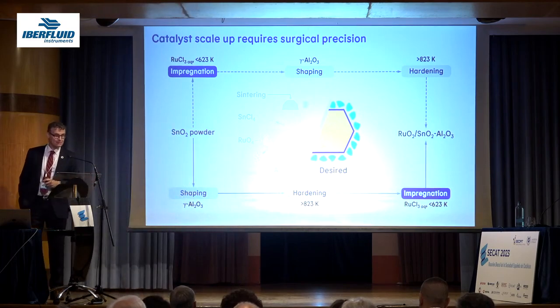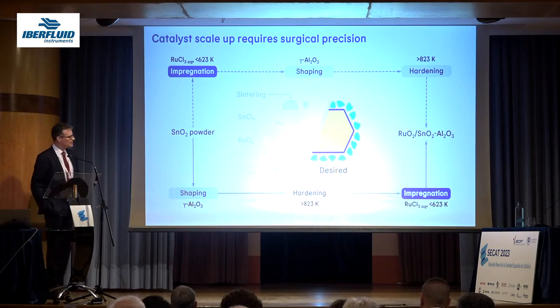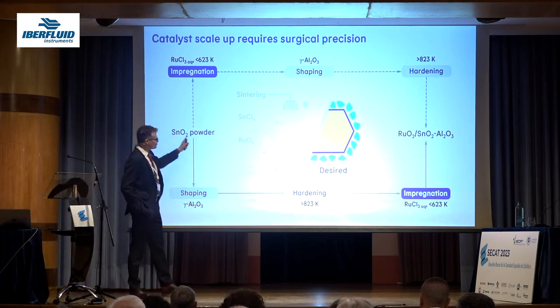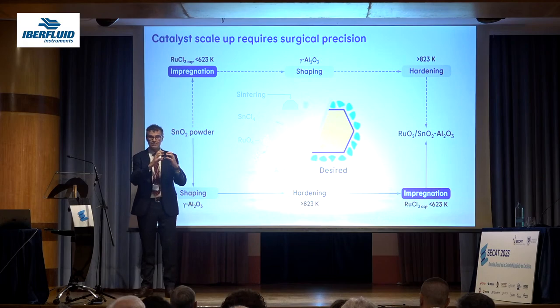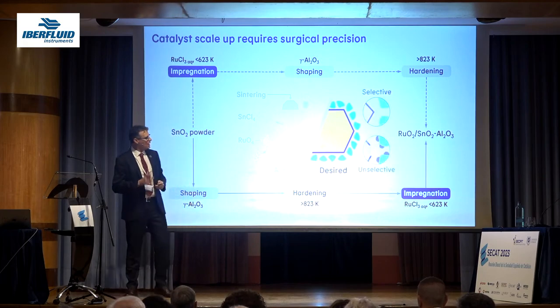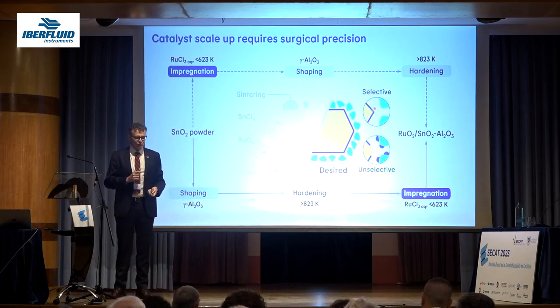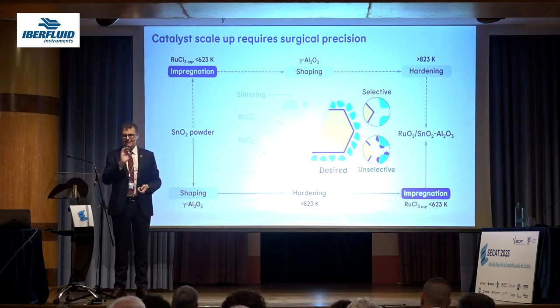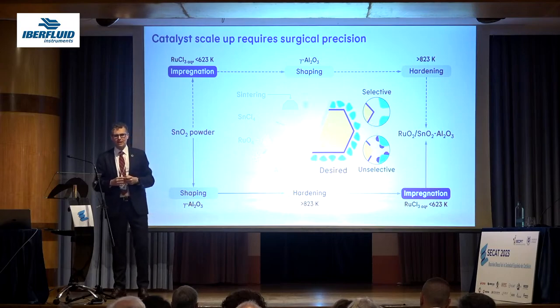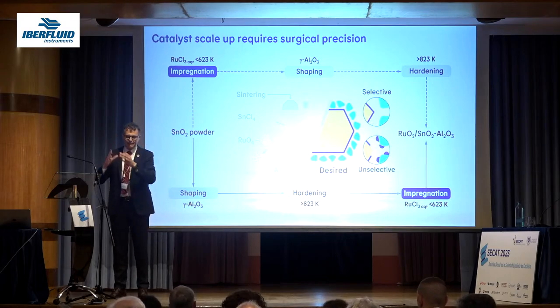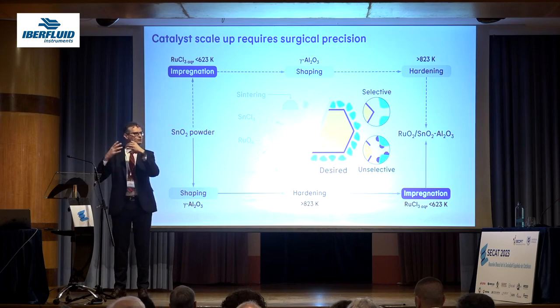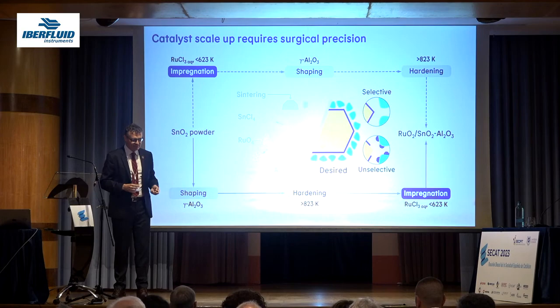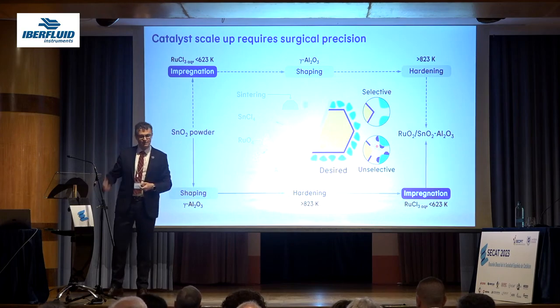And of course, the challenge, which also cost us 2.5 years, is that once you have a tin oxide alumina body, and you impregnate ruthenium, how to guarantee that the ruthenium goes all to the tin oxide and does not split between the tin oxide and the alumina? Because every ruthenium that ends up on the surface of alumina is going to be an inactive ruthenium and will leave the tin oxide naked. And you know what happens when you leave the tin oxide naked. You are going to volatilize the support.